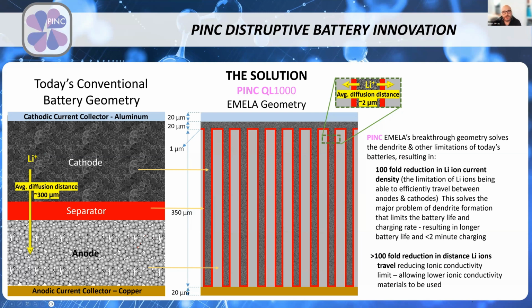And by reducing the distance that ions travel, we also improve this. So we rely less on the improved ionic conductivity of the material, because the distance that the ions travel is from several hundred microns, now reduced to a few microns. So in that sense, there is about 100-fold reduction in the distance that ions travel, and also there is more than 100-fold improvement in surface area, which brings down the ionic current density.